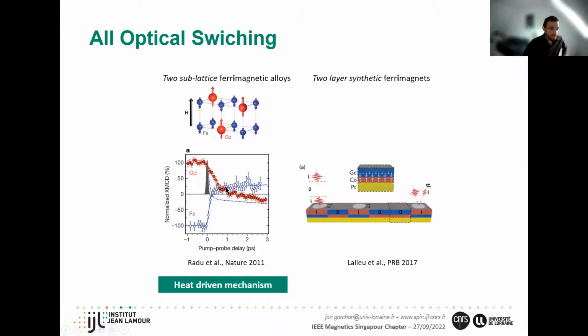So I won't go further into details. If you have any questions, you can ask me later. But basically, where I want to go is that some years later, it was discovered that you could get the same mechanism that you saw here with the synthetic ferrimagnet. So here, the group of Bert Koopmans grew a cobalt gadolinium bilayer, and they showed that you could get the same type of single shot, ultra-fast, all-optical switching. And so here, the fact that you're separating the layers means that you need to transfer angular momentum from the cobalt to the gadolinium and vice versa remotely. So this is a non-local mechanism, and so this requires spin currents. So we're getting back to the idea that you need these spin currents and that they're crucial for switching.